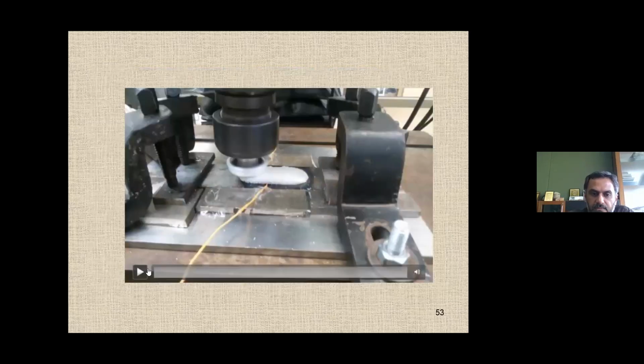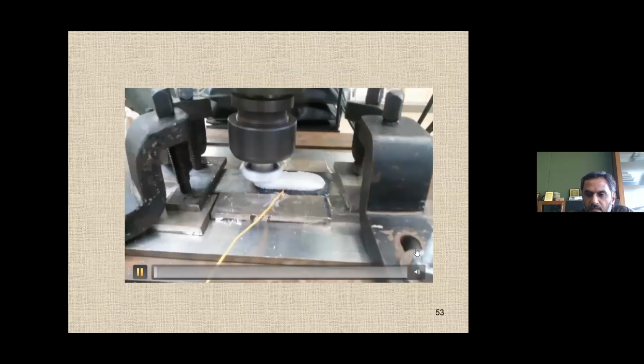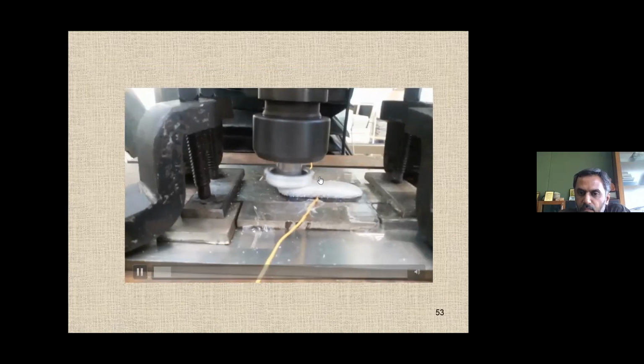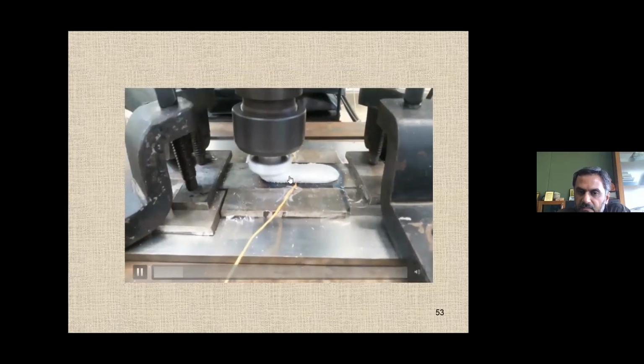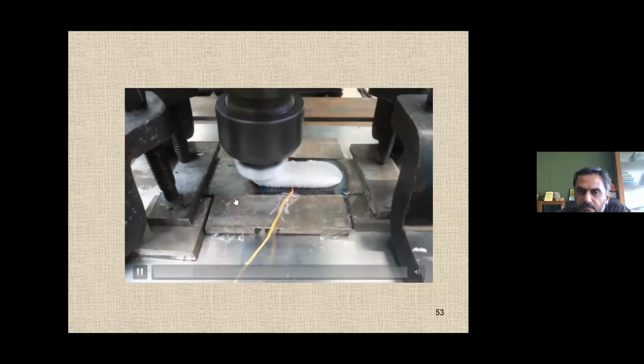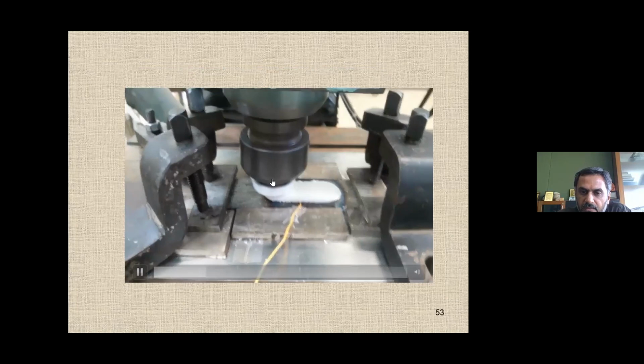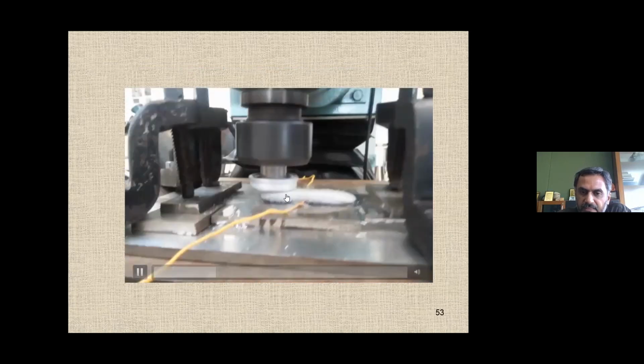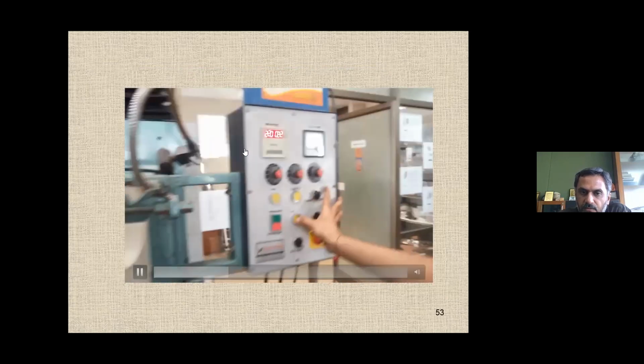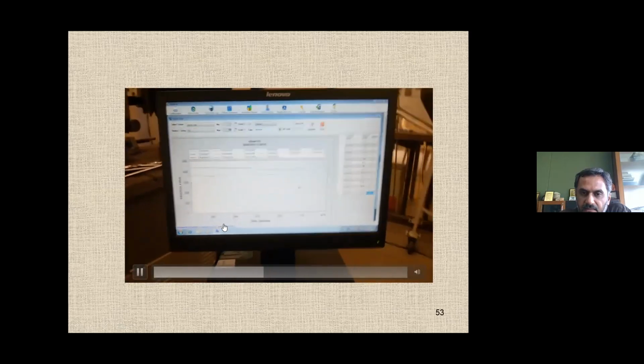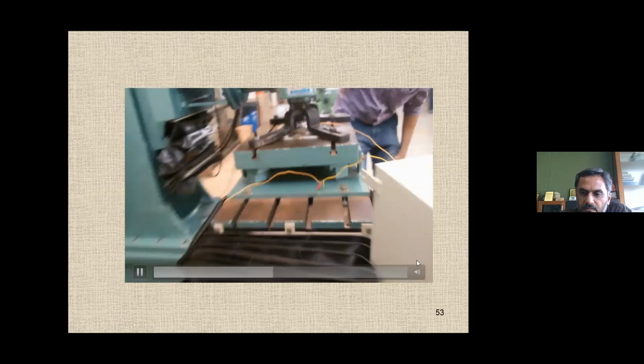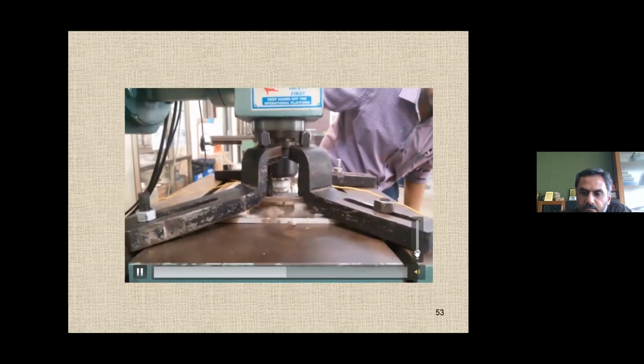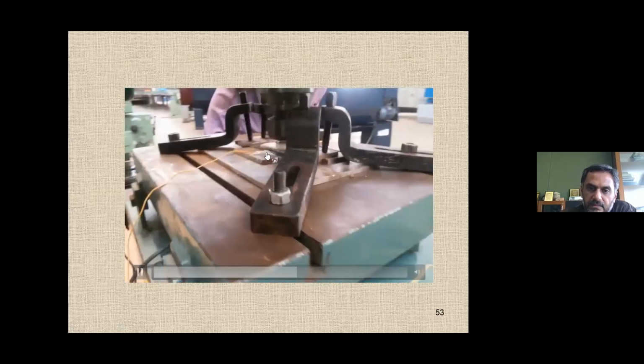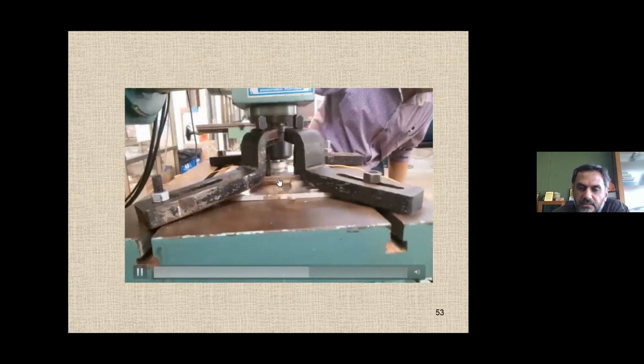So here you can see there is a small clip. This is again our own video. You see here there is an aluminum layer which has been created. So there is an aluminum rod which is tilted by 2 to 3 degrees, and you see the layer. And here you have around 2000 RPM, and the diameter of the rod you can see. And the temperature measurements are carried out on the advancing side and the retreating side. So you can see the aluminum layer which has been deposited here.